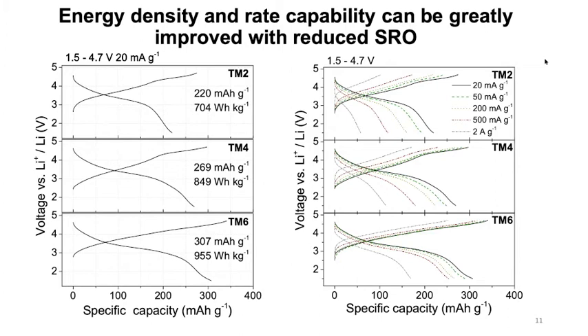As a consequence of the reduced short-range order, we can see the electrochemical performance can be significantly improved from TM2 to TM6. When we cycle between 1.5 to 4.7 volt at 20 milliamp per gram, TM2 shows a capacity of 220 milliamp hours per gram and a specific energy of around 700 watt-hours per kilogram. This can be improved to a capacity of around 270 milliamp hours per gram and a specific energy of around 850 watt-hours per kilogram, and can be further improved to larger than 300 milliamp hours per gram and a specific energy of larger than 950 watt-hours per kilogram.